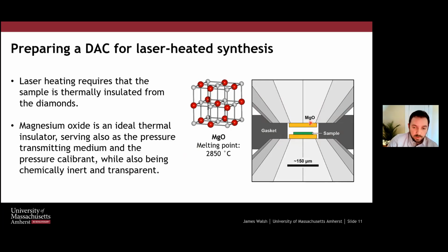Not only is it a thermal insulator, which insulates the sample from the diamonds. If you didn't have that, you'd be just heating the diamonds, and you wouldn't really be able to efficiently heat the sample. But not only is it a thermal insulator, it also serves as the pressure transmitting medium and the pressure calibrant as well. We know the equation of state of magnesium oxide, so that allows us to look at its lattice parameters to get the pressure that we're at in situ. And it's also chemically inert, we presume, with a very high melting point, and optically transparent. So really it's perfect all around for this purpose.